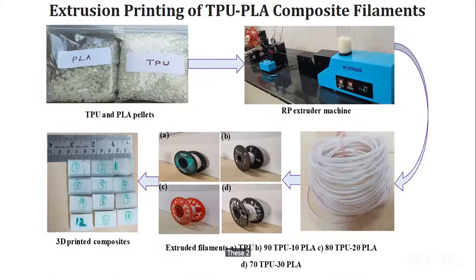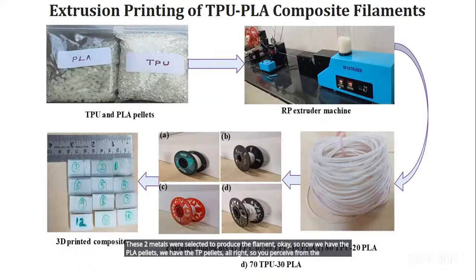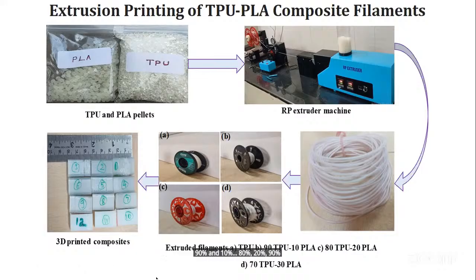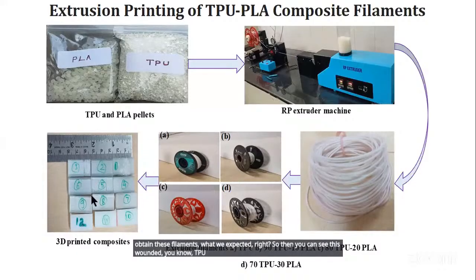Now, these two materials were selected to produce the filament. We have the PLA pellets and the TPU pellets, purchased from a reliable vendor. Then we used the single screw extruder machine in the mechanical engineering department, from one of my colleagues, who gave us this facility for extrusion of this TPU PLA composite. After various permutations and combinations, we were able to obtain this TPU PLA composite. Different combinations were tried, like 90% and 10%, 80% and 20%, 70% and 30%, and we were able to obtain the filaments we expected. You can see these wound TPU PLA composites, and these filaments were again used in the FDM printer to print compression samples. This is how we were able to make a new material system, that is TPU PLA composites. Okay, let us see some results on this.